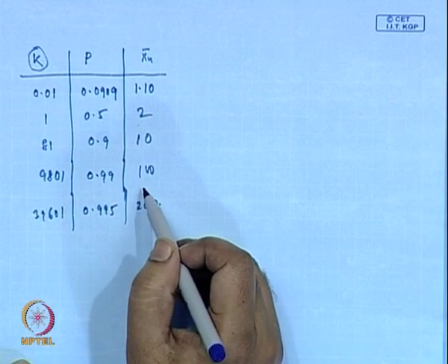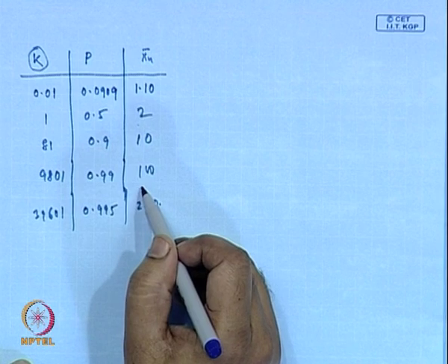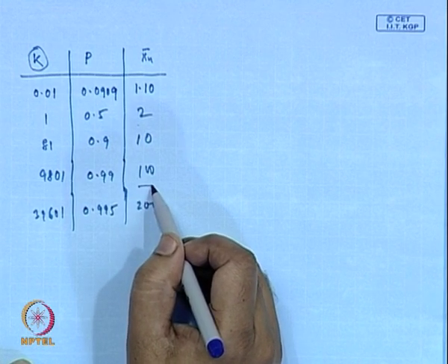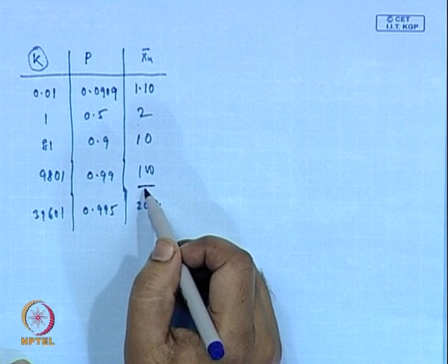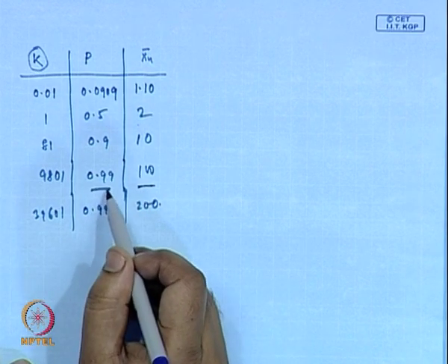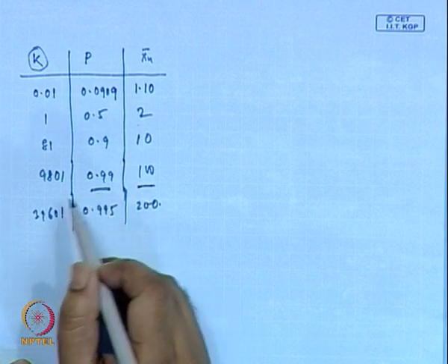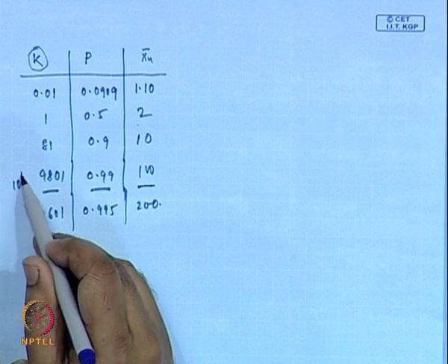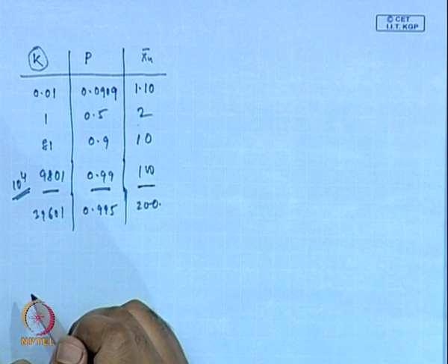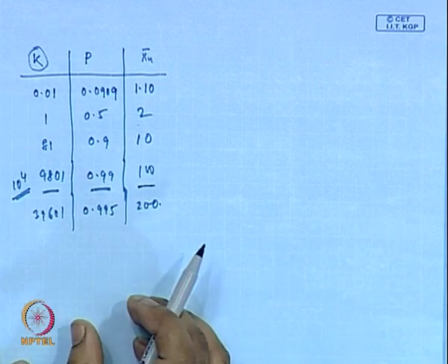If you want to build molecular weight, say a degree of polymerization of 100 in a closed system, then your equilibrium conversion has to be 0.99, which means your K has to be almost of the order of 10 to the power 4. That means, by itself your reaction has to be very highly reactive, so that without removing the byproduct you can get the product.